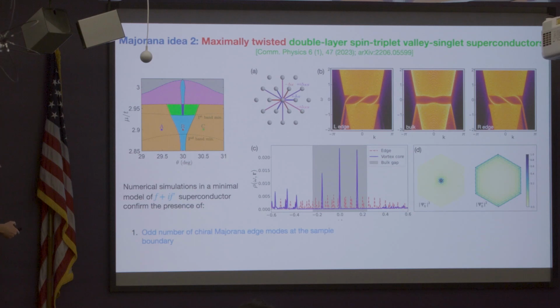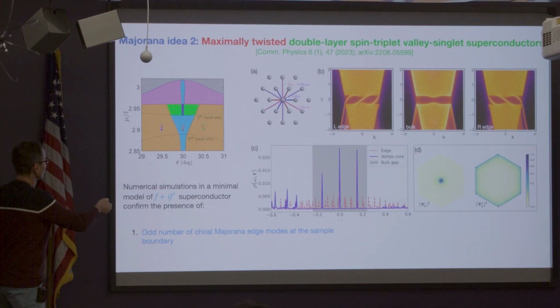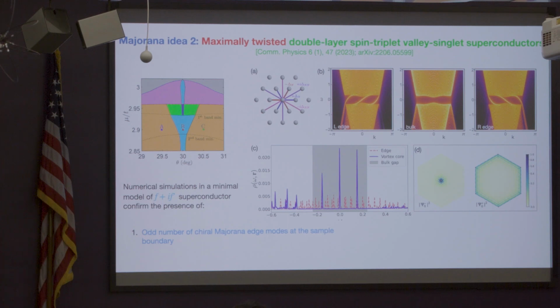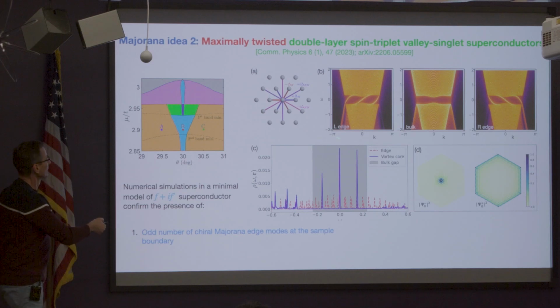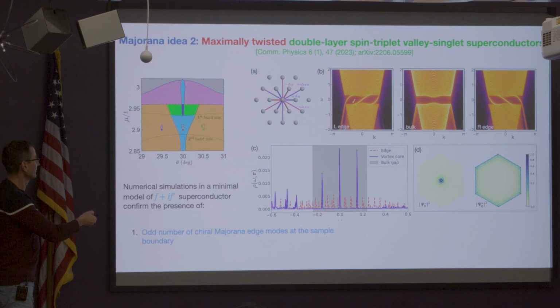We work on a triangular lattice. For those of you familiar with models of superconductivity, to model F wave, you need to put your superconducting order parameter on your bonds. And to do F and F prime, you need to use first and second neighbor bonds on this triangular lattice. Then you can put this on a strip, as we did with our cuprate. And this is the spectral function. So in the bulk, this is gapped, as you would expect. And this is the spectral function on the left edge and the right edge. So you can see that there are protected edge modes.